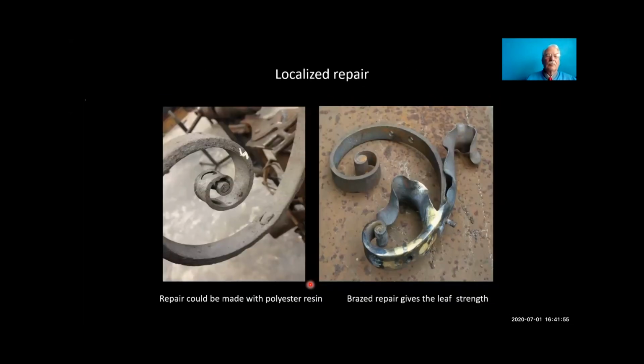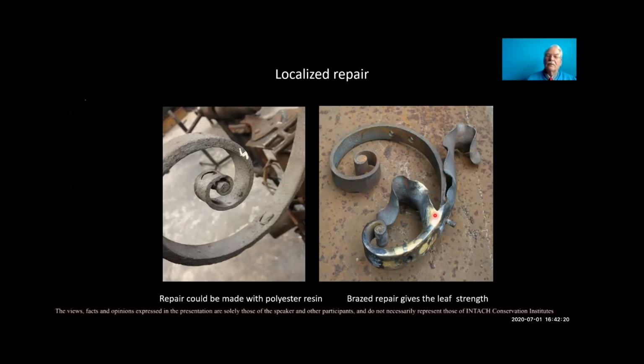Here, this could be a cold repair. In fact, you could simply fill that hole with a resin. If it's more extensive damage, this is gas welding on wrought iron. And here we've got brazing, that is using bronze as a filler. So you can see that it is, future generations can see that it is a repair. It's non-corrosive, and it can be done at about 900 degrees centigrade, or even lower if you use a different mix. And so it's much less dangerous for the metal itself, for the parent metal itself. That's a good way of carrying out localized repairs.